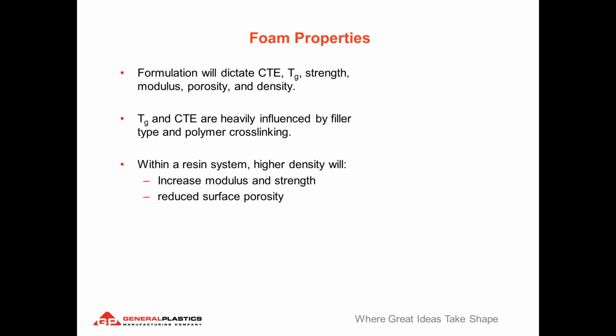And they're really heavily influenced by filler type and polymer cross-linking. And I mention that because a lot of the tech data out there is not all using the same ASTM method. And so it's really important to look at what the glass transition temperature and the CTE are over the temperature range that you're actually going to use the foam. So if you're doing an ambient cure, low temperature curing prepreg, you should be looking at CTE 60 degrees to 120 F. If you're doing a BMI resin cure, then the CTE and Tg should be considered all the way up to what the 350 F, 375 F cure is required.